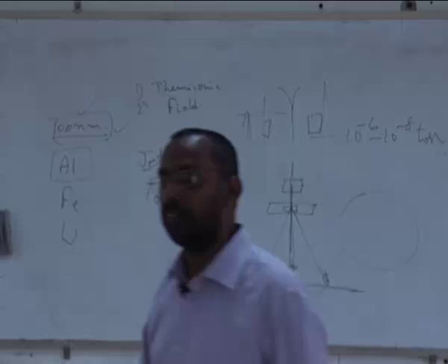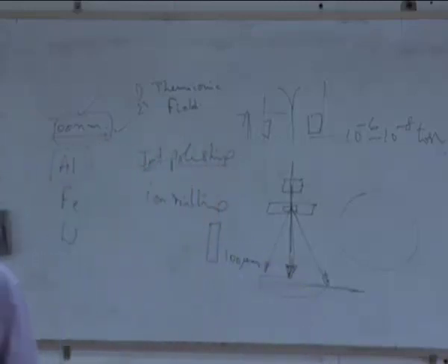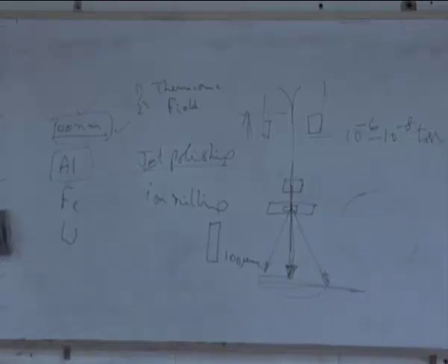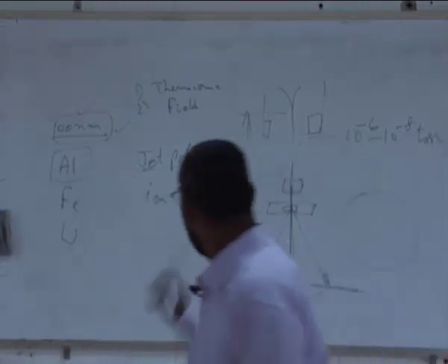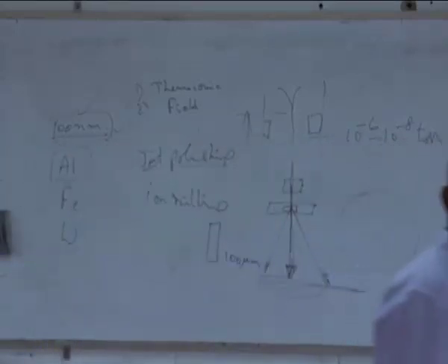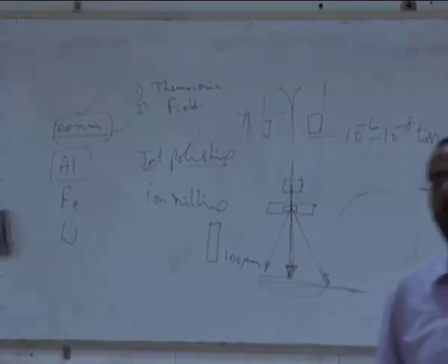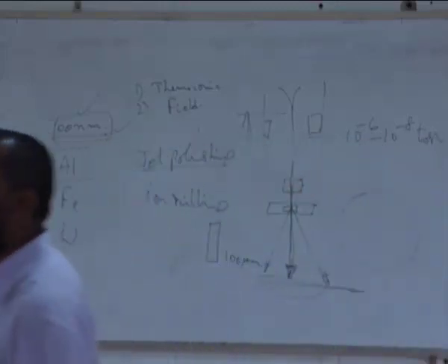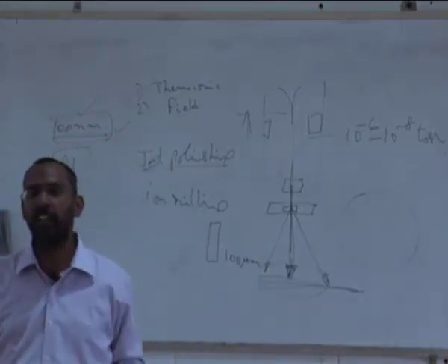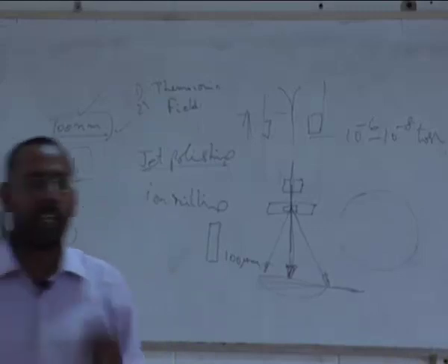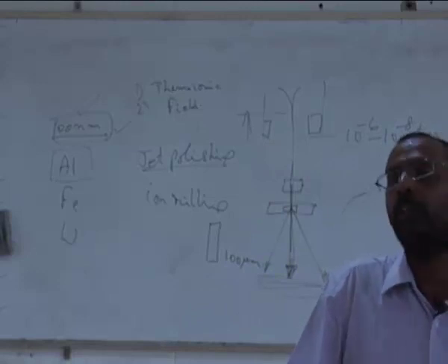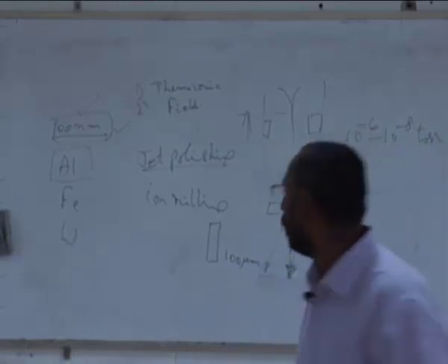Ceramic materials are very brittle. Slicing a ceramic material is not easy. The only way to make a ceramic material into such a thin sample is if you can somehow polish it without breaking it. So that's why handling ceramic materials is not very easy in a TEM. There are special techniques available, particularly ion milling, which can cut even a brittle material into very thin slices.